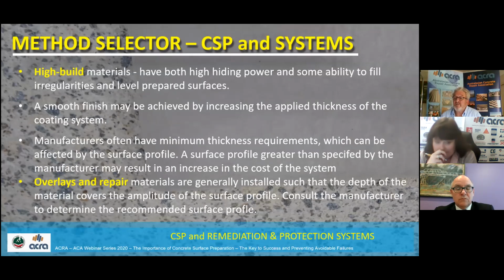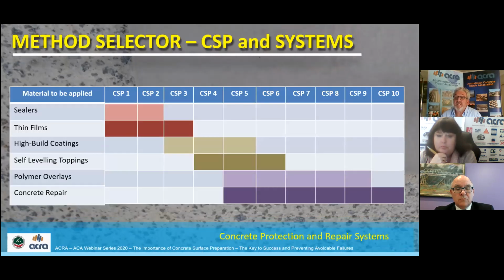Overlays and repair materials are generally installed such that the depth of the material exceeds the amplitude of the surface profile. You see there's a chart there that shows us the material to be applied and the surface profile that's recommended. Sealers go from CSP 1 to 2, thin build 1 to 3, high build 3 to 5, self-leveling like a flooring product goes 4 to 6, and the polymer overlay goes 5 to 9 with concrete repair 5 to 10.